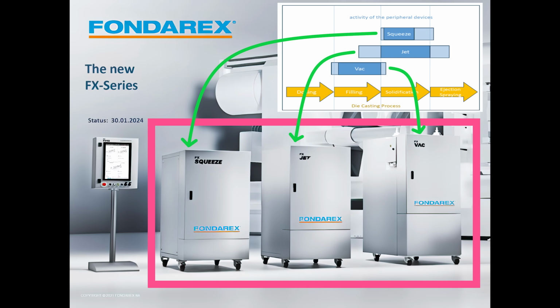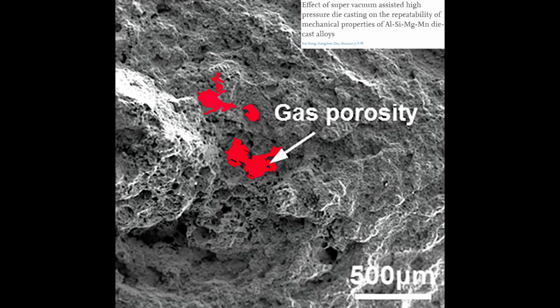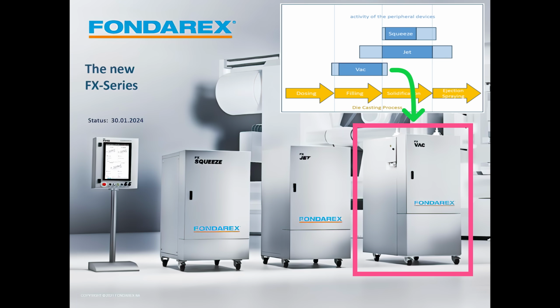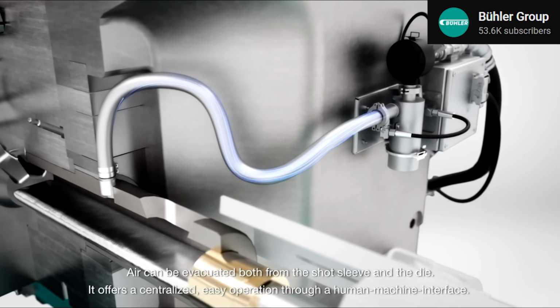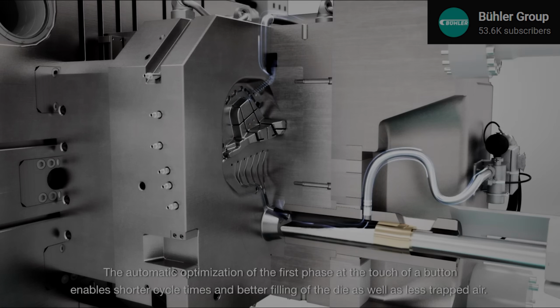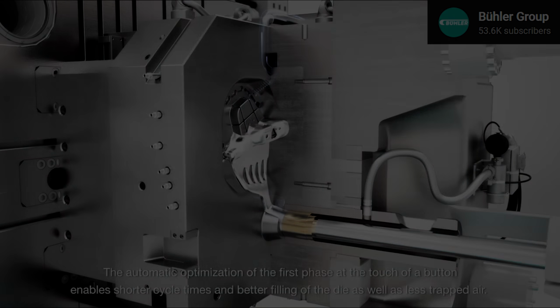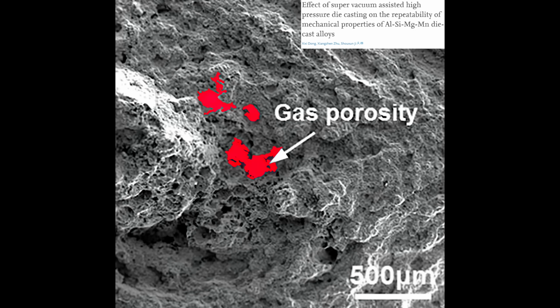Fondarex has three products that help with those technical challenges by reducing defects caused by gas porosity and shrinkage. Gas porosity is exactly what it sounds like. When the part is cast, gas becomes trapped in the part, which results in a weaker part. The gas porosity can be caused by something as seemingly benign as a drop of water, which can expand by 1,000 times when it goes from liquid to gas. To help solve that problem, Fondarex has a product called FX Vac. FX Vac is a vacuum die casting product, which is a technology I've talked about before. The die is placed under vacuum to remove air and moisture, which in turn reduces porosity. Due to the fact that I've covered vacuum die casting in other videos, and it's widespread in the casting industry, I won't cover it again in depth in this video.